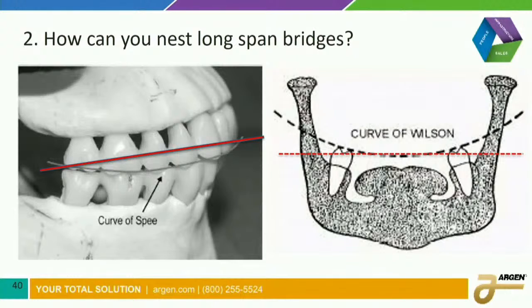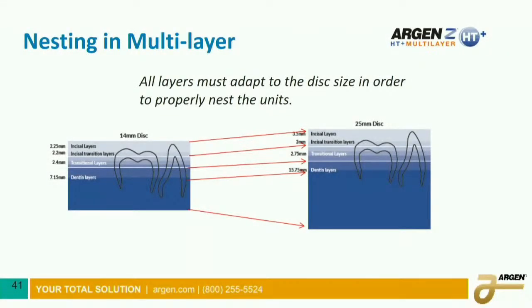Now, one of the things I indicated was why keep the incisal layer so thin? We didn't understand why they did that because long span bridges have curves to them. We have two natural curves in natural dentition, as you're aware of, the curve of Wilson and then the curve of Spee. And this is the reason why we need a thicker disc. Because as the curve increases, as the number of units increases, the curvature is going to go up, and we need to seat those units in that disc a little better, and we need a thicker disc to do that.